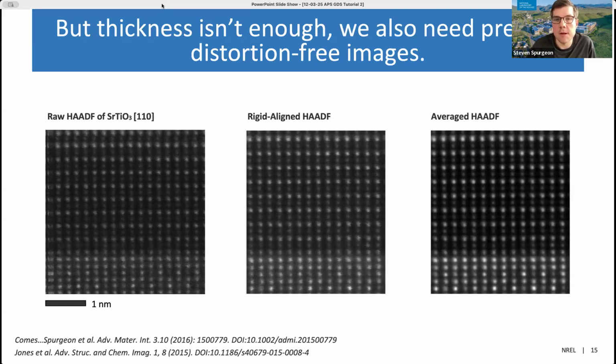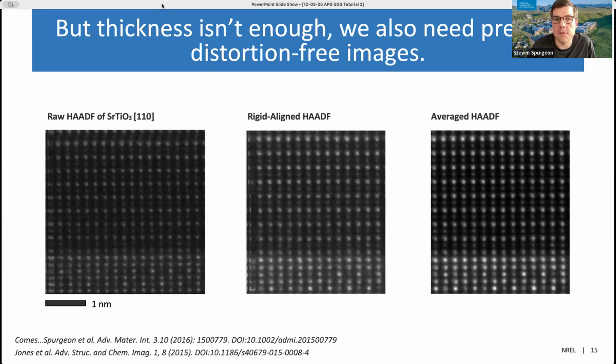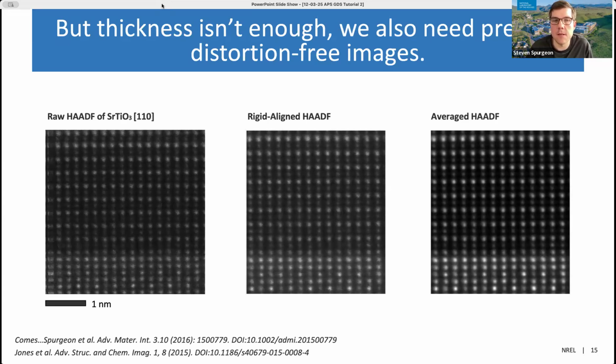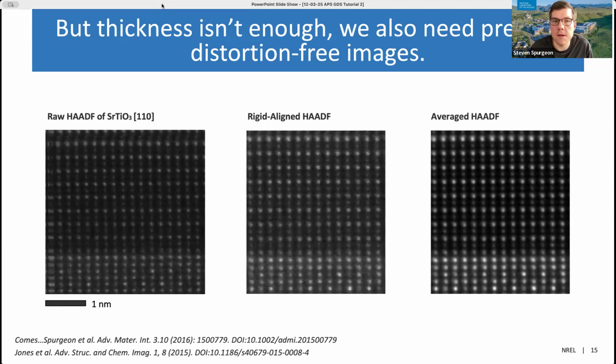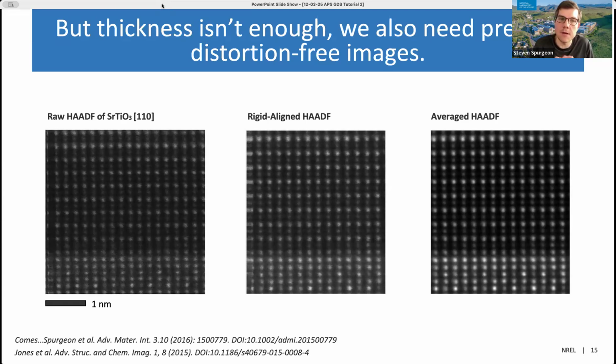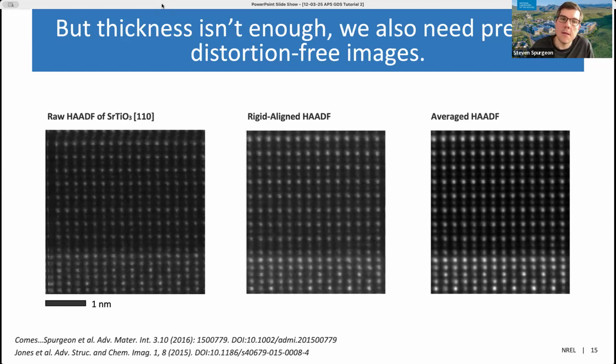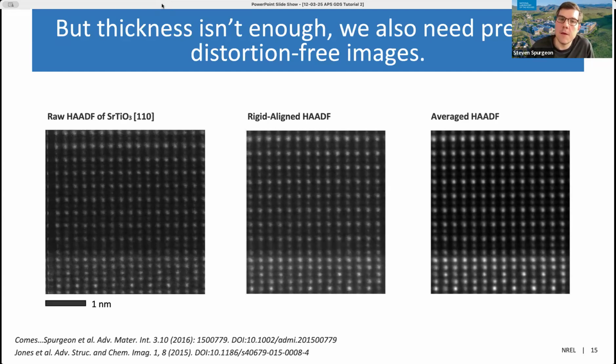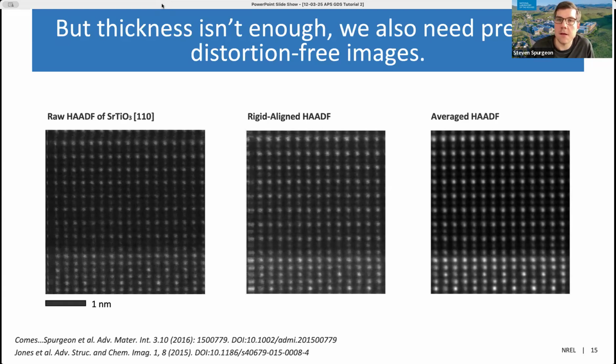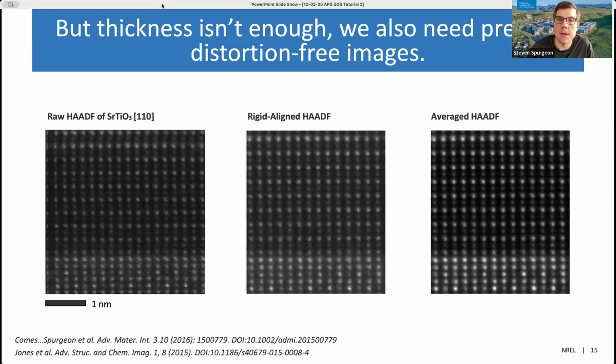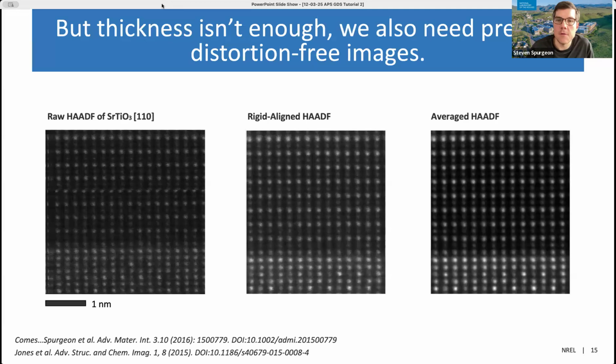We also look at other concerns. So when we're imaging things at incredibly high resolution, we're very sensitive to environmental disturbances. So what you're seeing on the left here, kind of linear thermal drift that can occur during imaging, and you see the atoms kind of dancing around and shearing laterally. This can all degrade the resolution of our imaging. And these sorts of artifacts are stochastic. They are random and depend on the environment from time to time. And so if you're trying to conduct some kind of campaign in reproducible analysis of materials, you need to be able to mitigate against these sorts of artifacts. Again, the goal here is to generate really good validatable ground truth data for a model.